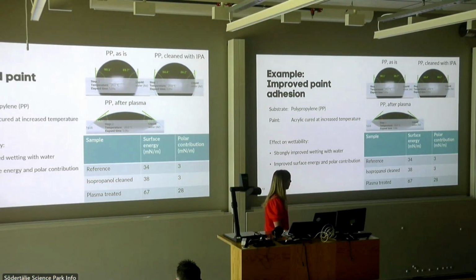Normally with polypropylene and other plastics, you are around 25, 30, 35 millinewtons per meter, and then you can put it up to 60 or 70 with the plasma treatment.